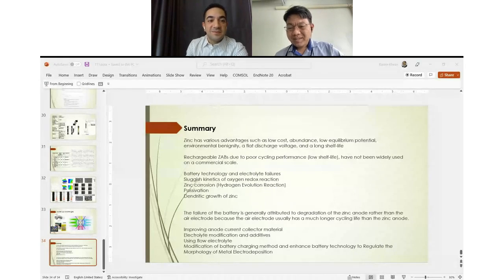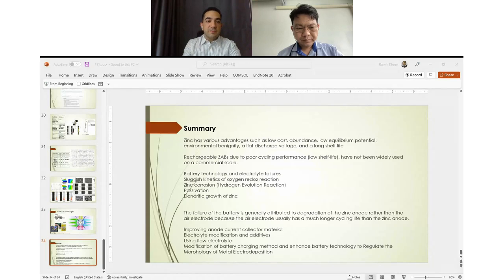Yes. Okay, so we have one question from Professor Ahmad Asmin asking about the air cathode. Comments on the air cathode. What is the best material now? Actually, for zinc battery, the air cathode usually needs a porous structure of carbon, usually carbon material doped with transition metals or sometimes transition metal oxide like manganese oxide, or sometimes we can use cobalt or nickel or iron doped on the structure of carbon in order to fabricate an air cathode. But it should be conductive enough, and also we need to consider that the gas diffusion layer should be hydrophobic in order to save the water content of the system.